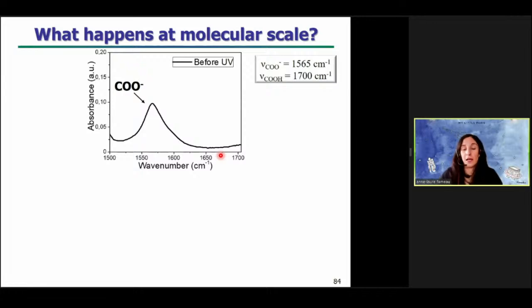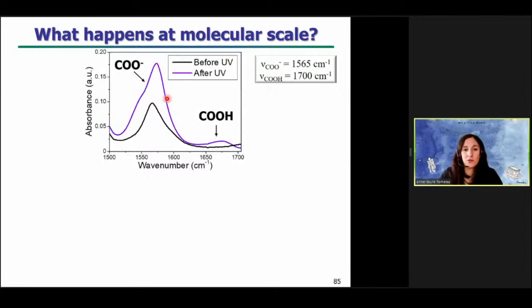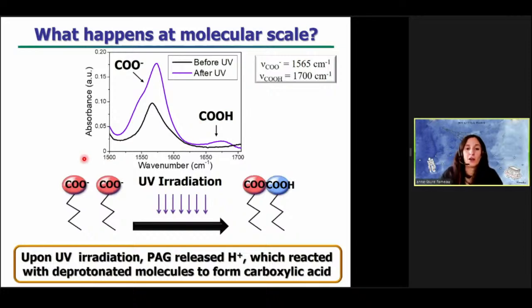For this, we used infrared spectroscopy measurements. And here you can see that before UV radiation, we have just one peak corresponding to the presence of fatty acid under ionized state. After UV radiation, you can see two peaks. So you still have the first peak corresponding to the fatty acid under ionized state, but you have a second peak corresponding to the presence of protonated fatty acid molecules. So before UV radiation, all the fatty acid molecules are under ionized state. You put your sample under UV radiation, and you have a mixture of protonated and deprotonated fatty acid molecules. So upon UV radiation, the photoacid generator molecules release protons that interact with the deprotonated molecules to form carboxylic acid.